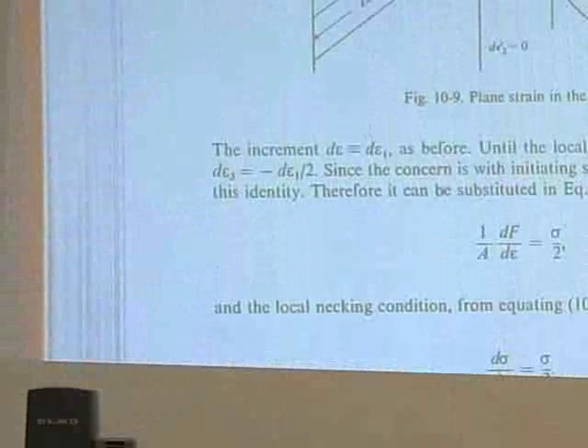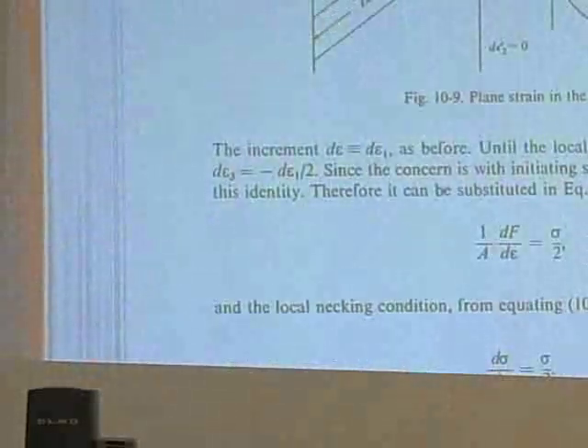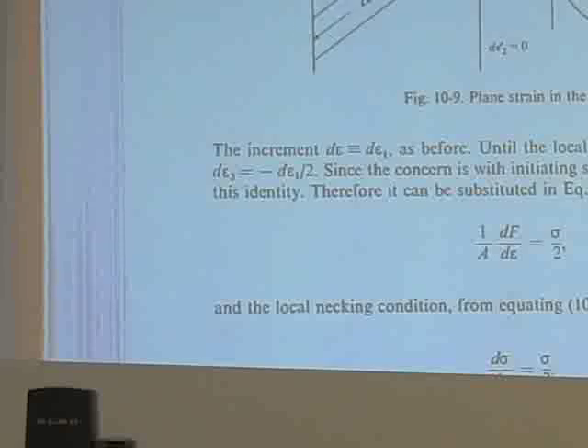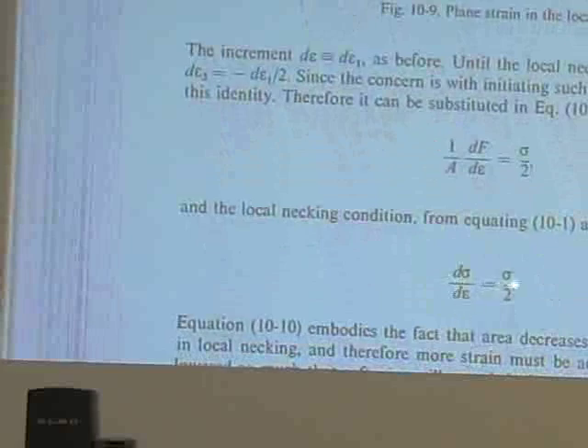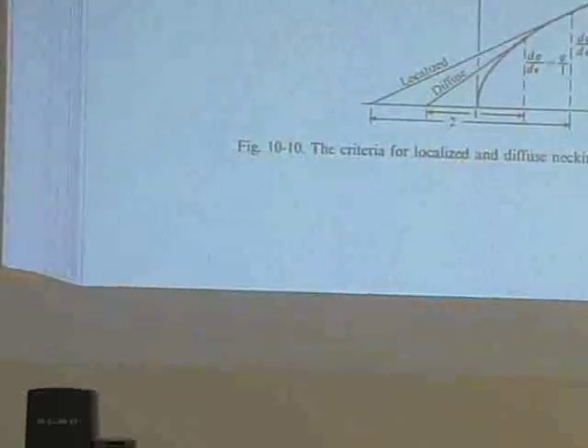It turns out that you can prove for sheet metal where you're getting zero extension in one direction, but the other direction is not plane strain, that the criterion of d sigma d epsilon for local necking in sheet is sigma over 2. And so if you look at sheet metal and you do the Considère construction, you actually have diffuse necking at epsilon equal to n, and you'll have localized necking at 2n. Okay? So you can have localized and non-localized necks in sheet metal drawing, or diffuse necks and localized necks.